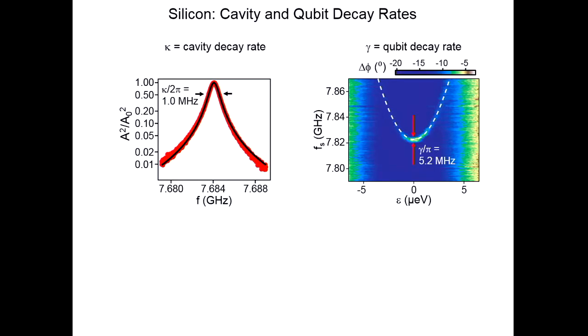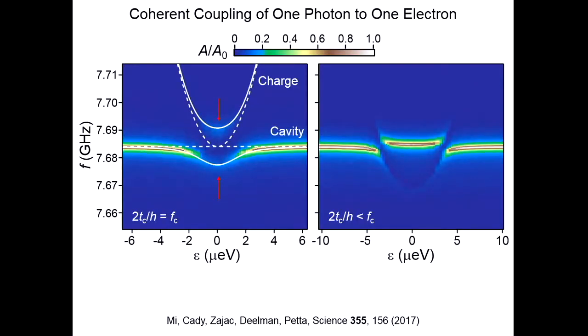But with these silicon devices, we now have respectable line widths that are on the order of a few megahertz generally. And so we can end up in a spot where you can really see the vacuum-Rabi splitting, the interaction between a single electron and a single photon. What's plotted here is the transmission through this cavity as a function of the tilt of the double well potential and as a function of the frequency of the light that we're shining in the cavity. The bright spot here, this line, is just the cavity resonance frequency. You get a lot of photons through the cavity on resonance.